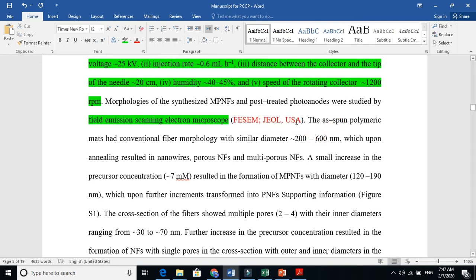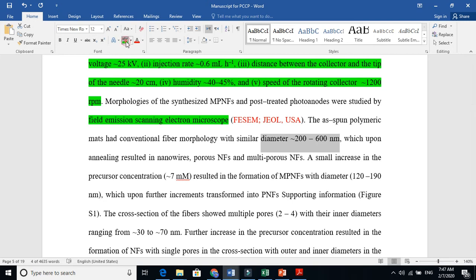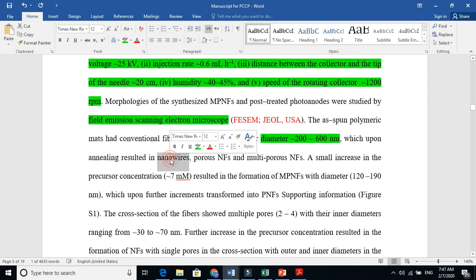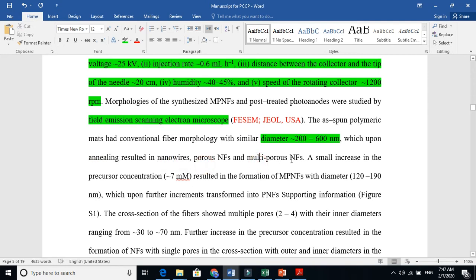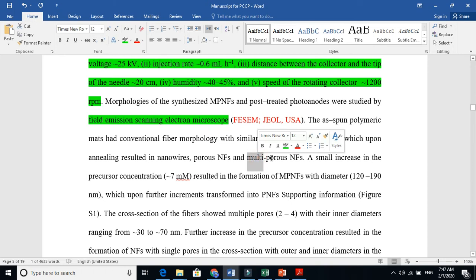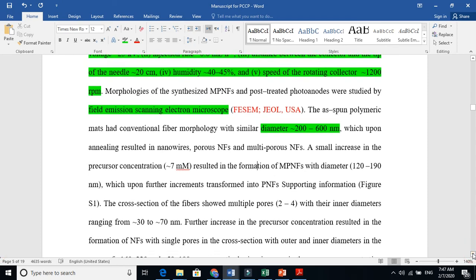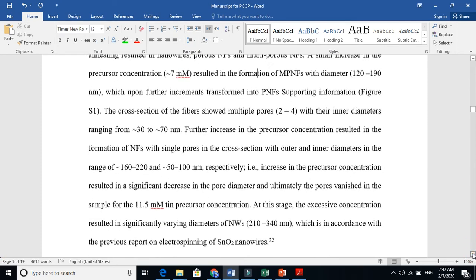You must need to let the people know. And when we did this characterization, what were the size of the fibers? The size of the fibers were in 200 to 600 nanometer. And it was before annealing. Annealing means heat treatment. When we did annealing of the nanowires or nanofibers, we got porous nanofibers. There were multi-pores, multi-holes. And I just explained further stuff here. Let's come down here to the synthesis part.